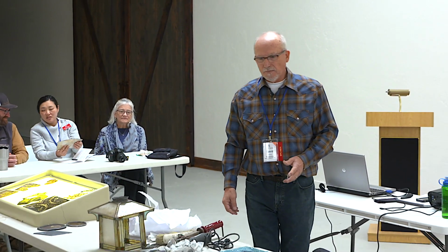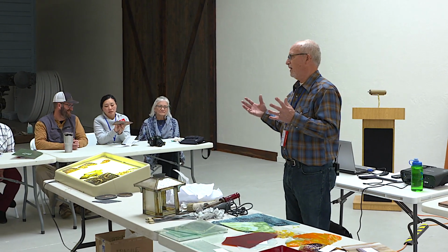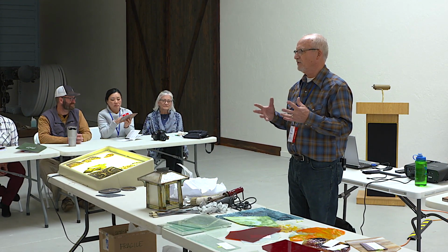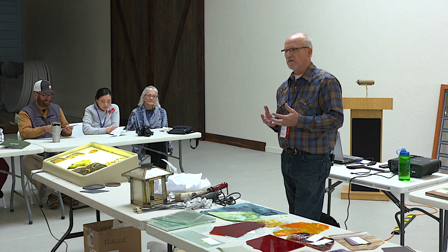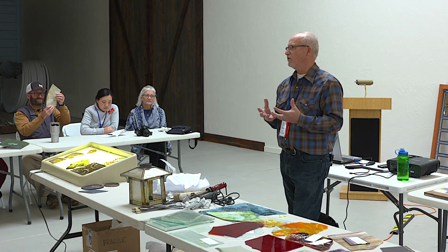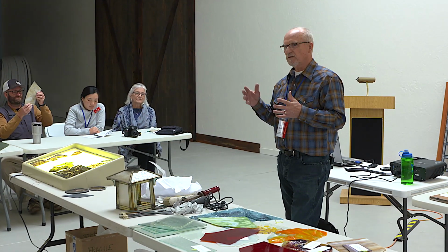So in our glass furnaces, if we take our basic potash and soda and silica and melt it down, we're going to come up with a clear. Glass oftentimes works like an acid. It dissolves whatever it's next to. Since it's like a lava, super hot and a liquid, it's dissolving the furnace walls or the steel crucible or the ceramic crucible. And so you never really get a pure clear. There's always some type of contaminant in it. But other than that, if you start adding your metal oxides and stirring them in, you can make different colors of glass, and those would be called pot metal.